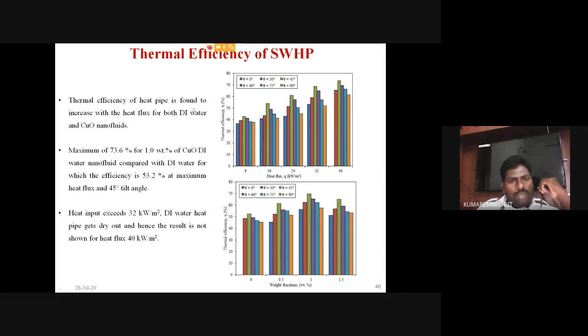The thermal efficiency of the heat pipe is found to increase with increasing heat flux for DI water, and the copper oxide, as well as the aluminum oxide nanofluid. The maximum of 73.6% thermal efficiency is attained for a 1 weight percentage CuO DI water nanofluid, compared with the DI water, for which the efficiency is only 53.2% at the maximum heat flux and the inclination angle of 45 degree.